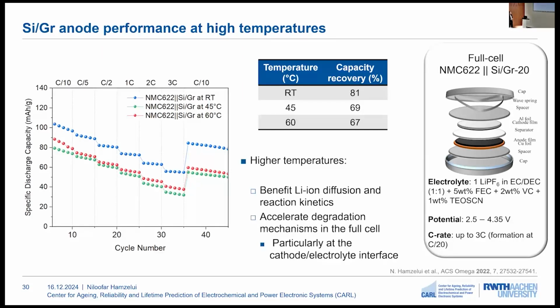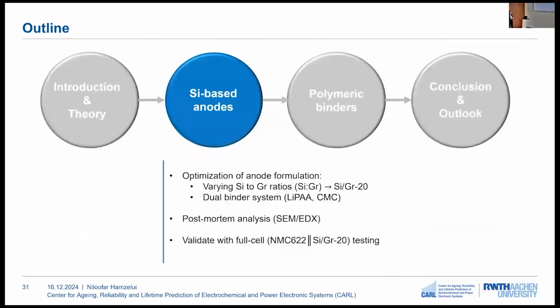And here we can see that the cells at higher temperatures show a lower capacity compared to room temperature. We can say that with increasing temperature, there is a benefit of lithium-ion diffusion and increased reaction kinetics. But on the side, this also increases the degradation mechanisms, especially in the full cell and in the cathode electrolyte interface, resulting in less capacity compared to room temperature.